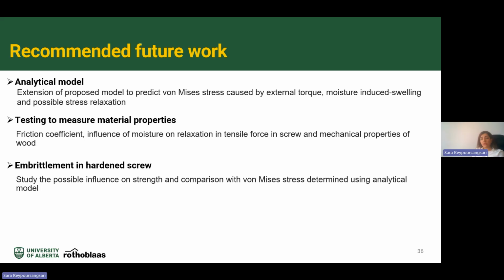Future experimental work should be focused on measuring the friction coefficient as well as assessing the effect of the moisture on relaxation in tensile force within screws, and also the effect of the moisture on properties of the wood. Regarding the hydrogen embrittlement in hardened screw, it is suggested to evaluate a potential influence of the embrittlement on a screw's strength and compare these findings with von Mises stress resulted from the analytical model.